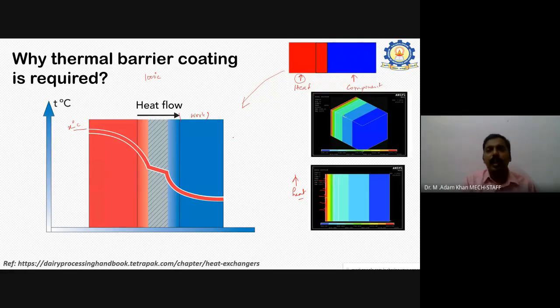If the material is directly exposed to this condition of 1000 degrees centigrade, what happens? If it is iron or nickel, it goes directly to recrystallization or a melting phase. Metallurgical phase transformation is directly involved here, and the material is metallurgically diffused, or metallurgical degradation starts. We cannot expect that component to have a reliable life at that higher temperature. To increase the reliability of the life, they produce these barrier coatings to reduce the temperature to some extent.